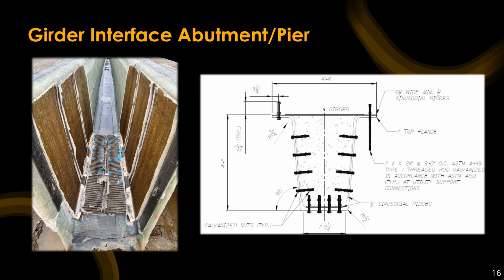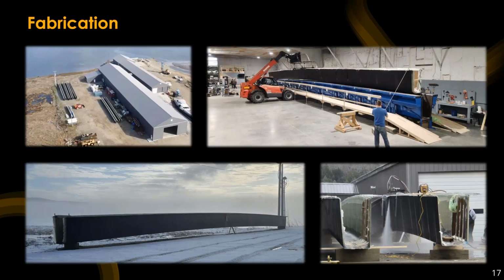So in terms of the fabrication, let's talk quickly about it. This is where we are taking it out of the mold. The mold has the camber of the girder in it. So we have calculated the deflections under the cast-in-place concrete deck, and we have added the deflections for all the superimposed loads, like the sidewalk and the wearing surface. And from that, we have set a camber profile for the girder. This is the girder sitting outside with a nice backdrop of snow and fog over the river. And in the right corner, we have water jetting the FRP girder after it comes out of the mold, to make all the edges look straight and nice and pretty.